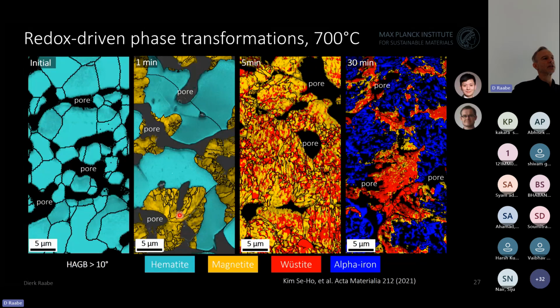These two crystal structures are not commensurate, they are incoherent, and you have correspondingly incoherent interfaces that form with many additional new grain boundaries. And the nucleation, not surprisingly, as we learned from the atomistic simulation, starts, of course, at the available free surface. The hydrogen itself, by the way, is not a bottleneck because it kinetically sweeps the material very, very fast. That means before any process in the interior arrives, the hydrogen is already there. So the bottleneck is the oxygen transport, not the hydrogen transport, as far as we can tell.